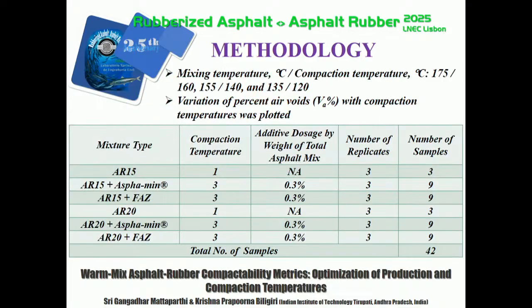The methodology is that we prepare the control AR mixture at 175 and 160, and then the warm mix asphalt rubber mixtures were compacted at 3 different compaction temperatures, and the variation of air voids with compaction temperature was plotted to match the air voids content that gives the same performance.